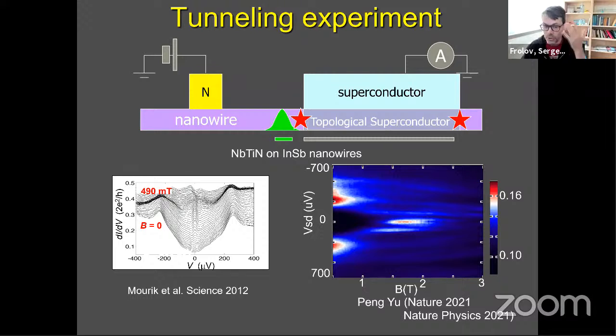And that is unusual because, like I said, in indium antimonide, G factor is 50. So some kind of state that has spin, an electronic state, should move very rapidly through the screen. For instance, in 1 Tesla, it might acquire Zeeman energy of 1.5 milli-electron volts. So on the right side here in color, if we start at 1 Tesla, we go to 2 Tesla, we expect a resonance that starts on the bottom and crosses all the way across, if it's due to a quantized electronic state with a G factor 50. So the zero bias peak here in the middle of the screen is dramatically robust. So over a 1 Tesla, we can see it kind of pinned to zero. And so that's what we explore as a signature of Majorana fermions.